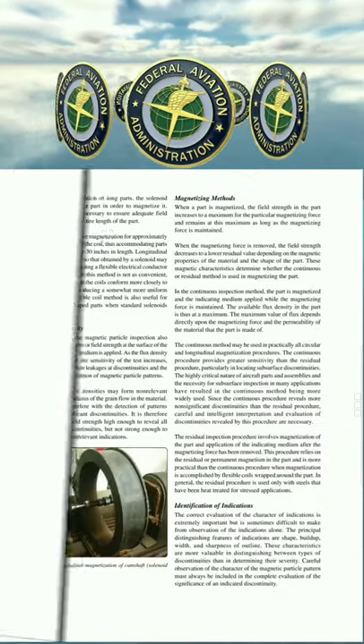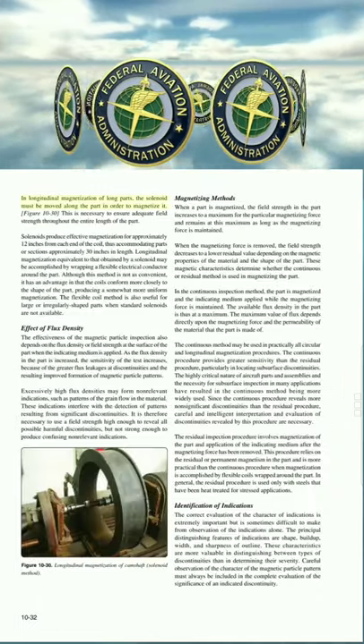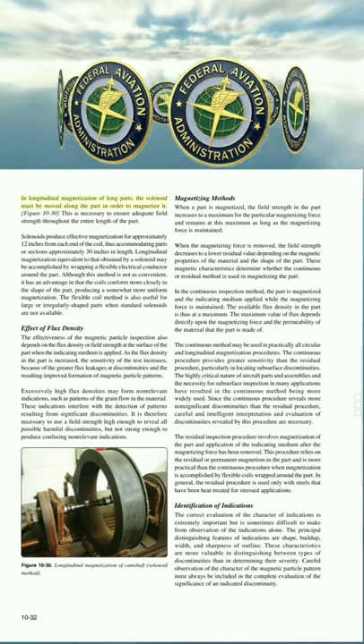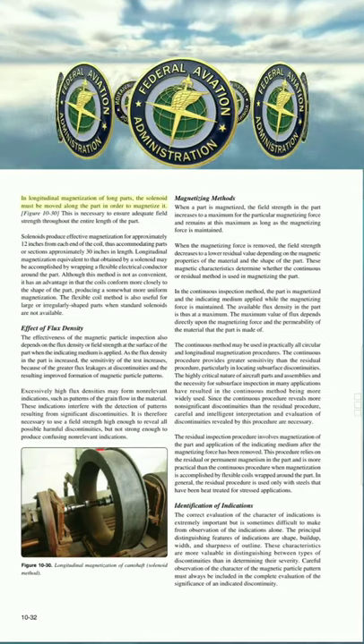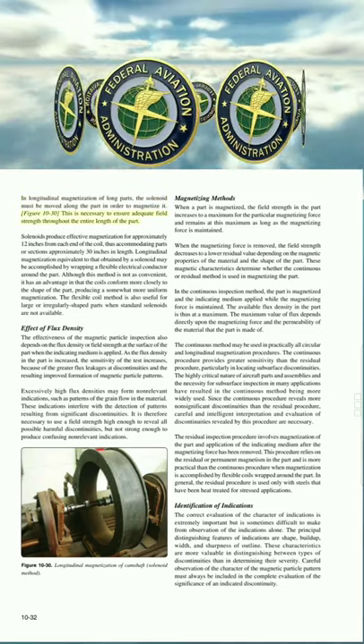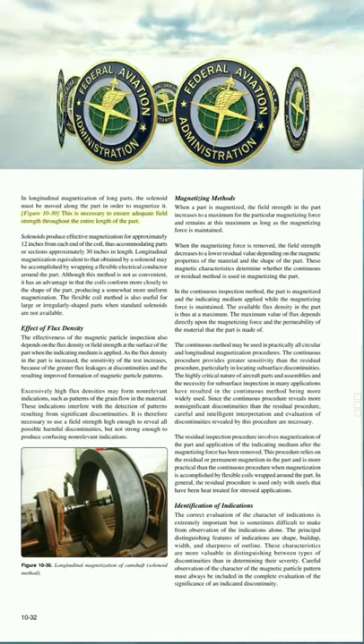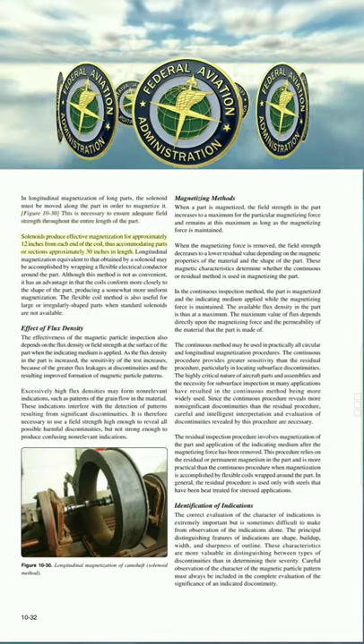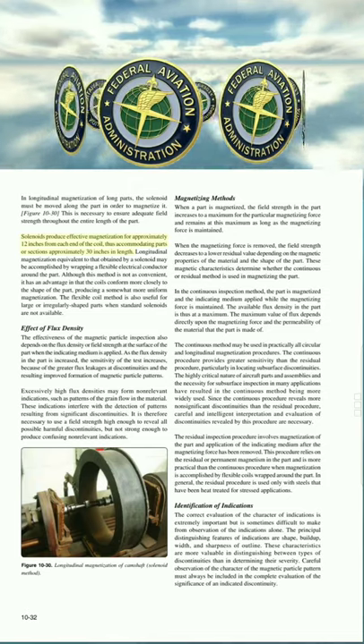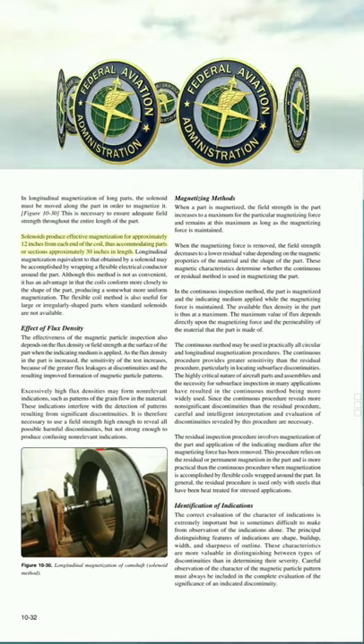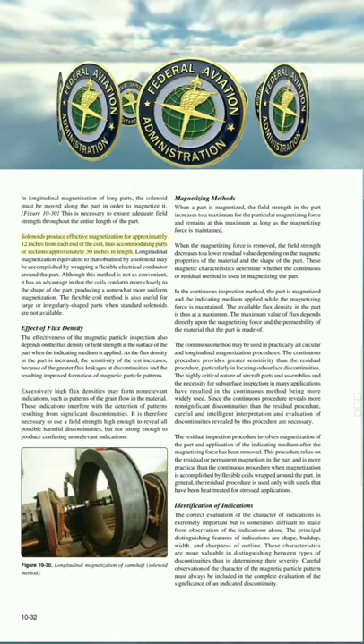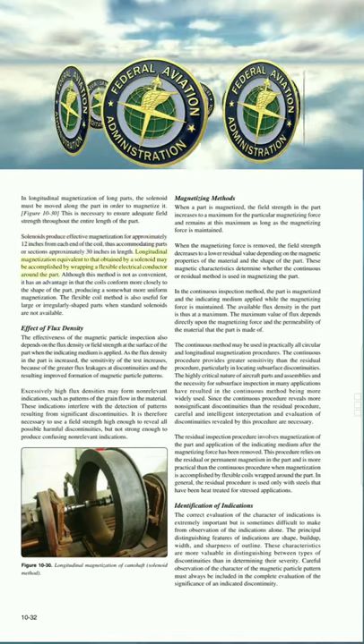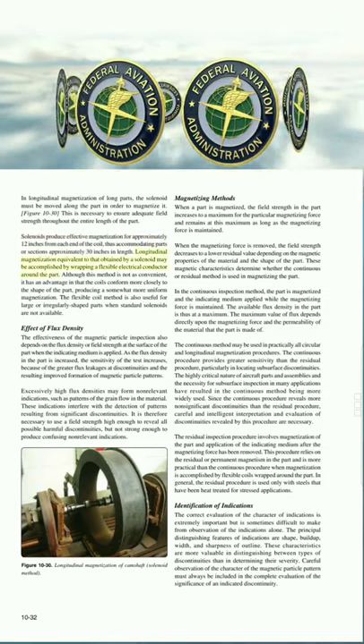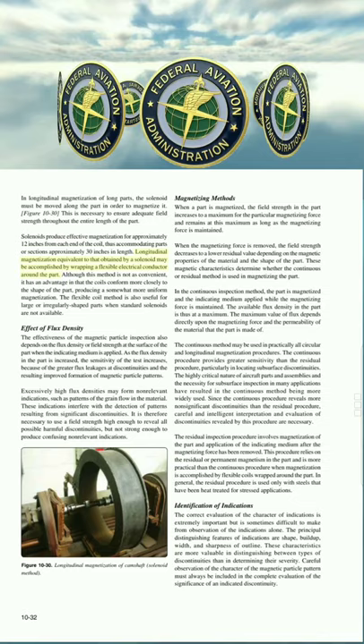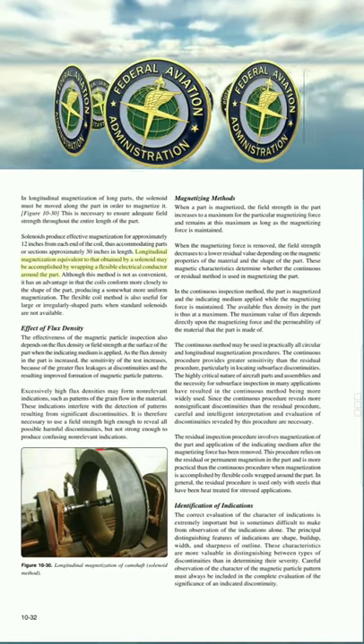In longitudinal magnetization of long parts, the solenoid must be moved along the part in order to magnetize it, Figure 10-30. This is necessary to ensure adequate field strength throughout the entire length of the part. Solenoids produce effective magnetization for approximately 12 inches from each end of the coil, thus accommodating parts or sections approximately 30 inches in length. Longitudinal magnetization equivalent to that obtained by a solenoid may be accomplished by wrapping a flexible electrical conductor around the part.